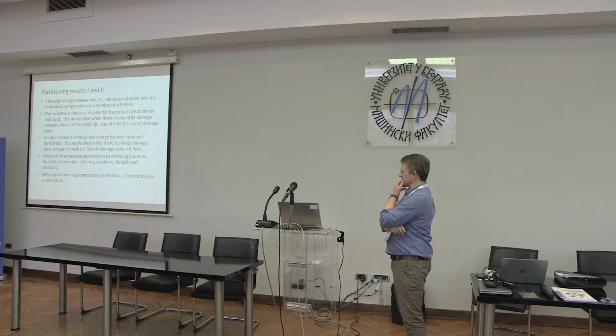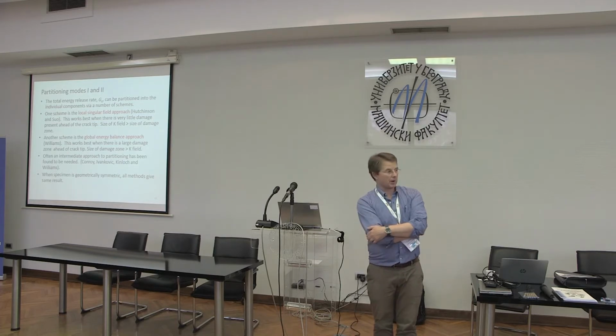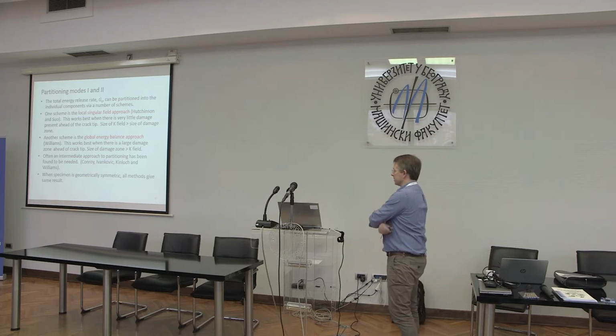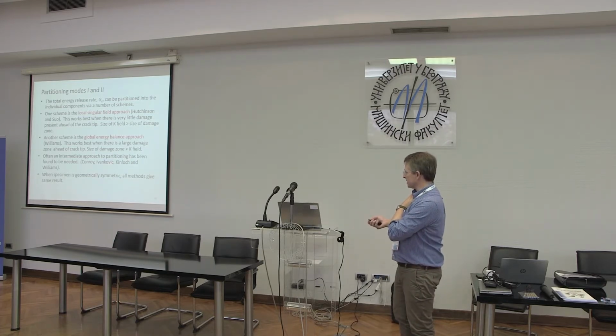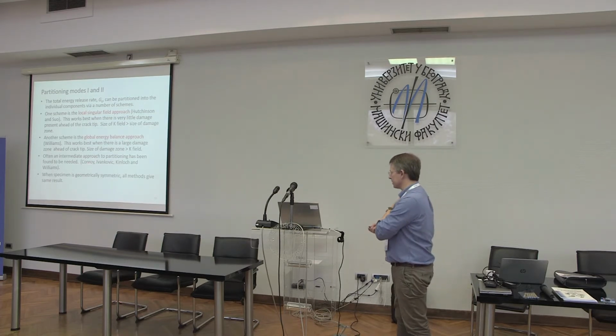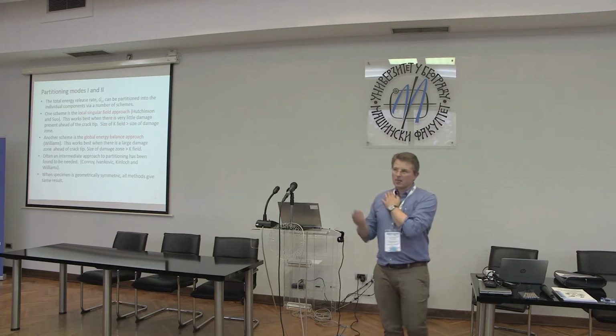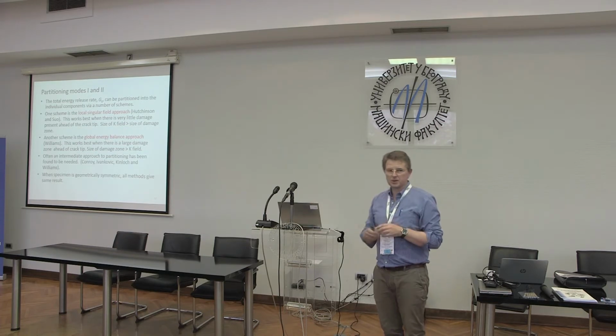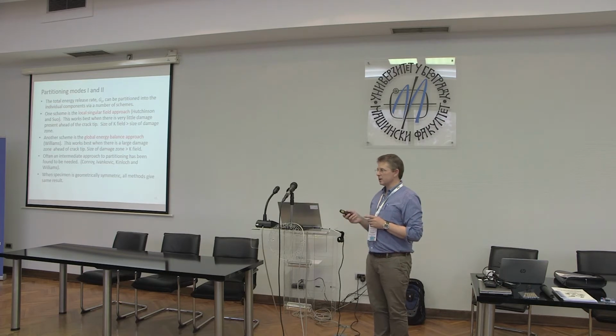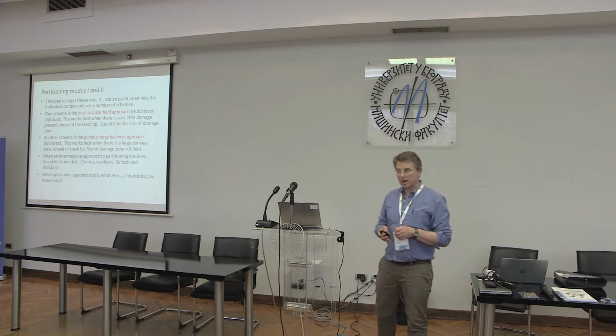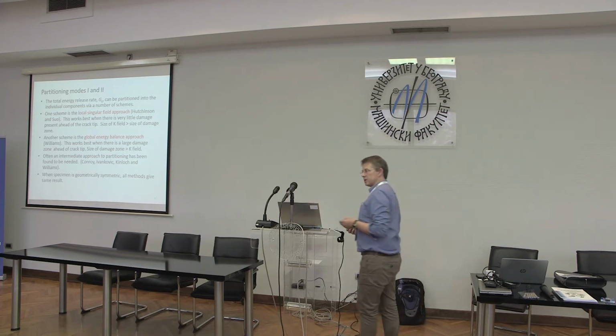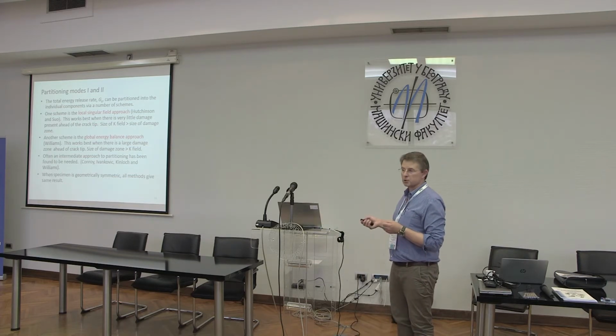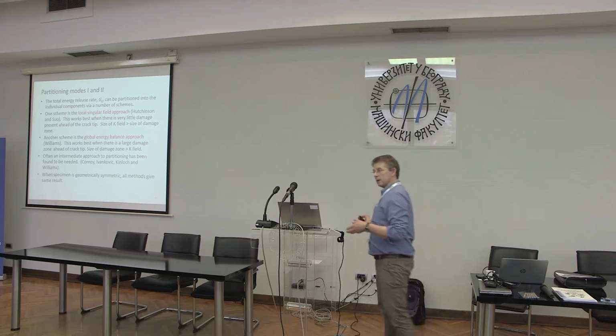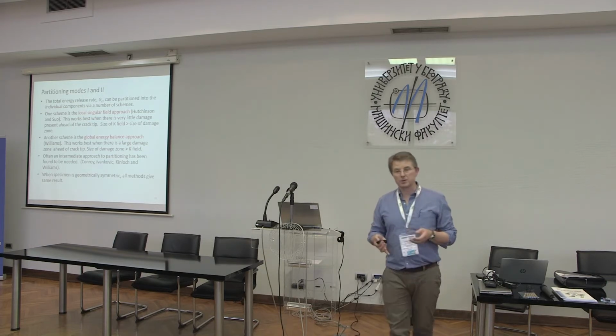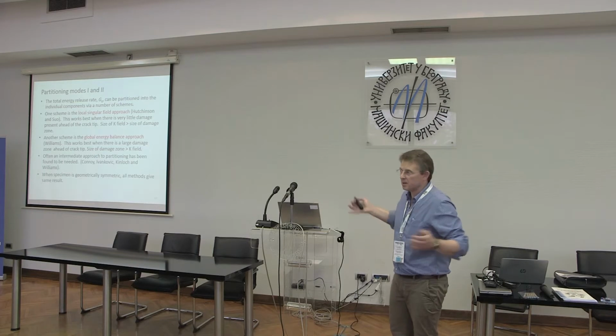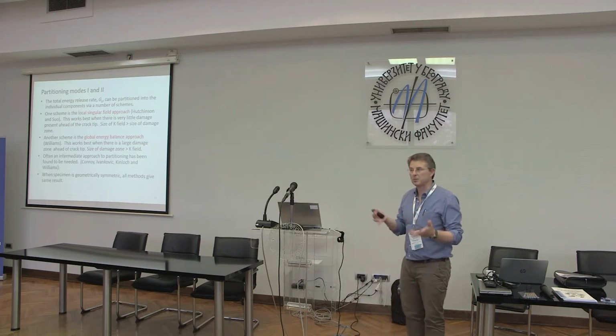So the way to rationalize it is that it depends upon the degree of damage at the crack tip. And what we found, and there's been some excellent recent work by, for example, the guys at Dublin, Conroy and Ivankovic, and also working with some of my colleagues at Imperial College, looked at quite a wide range of different materials. And it comes down to the degree of damage at the crack tip. So for materials where you have a very small damage zone that are behaving in a brittle fashion, to partition those energy release rates, it's best to use a local singular field approach. So you don't use a global analysis as proposed by Gordon Williams in that earlier work. You use this local field analysis proposed by Hutchinson and Suo and others. For example, Barry Davidson in the United States came up with a relatively similar partitioning scheme.